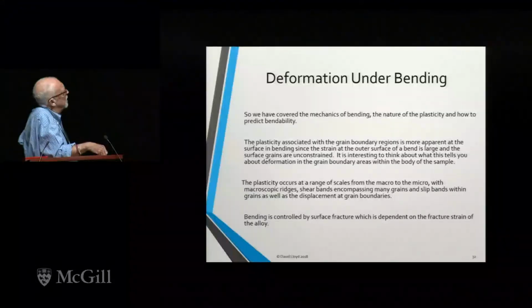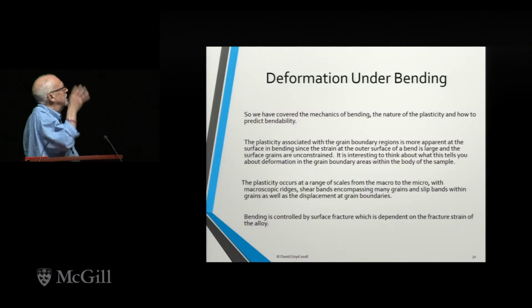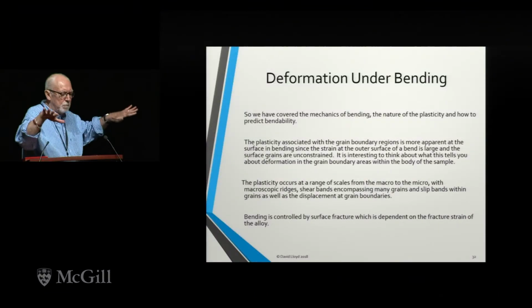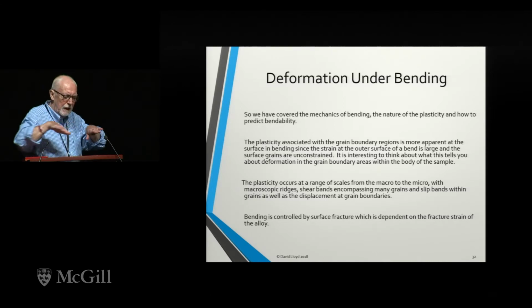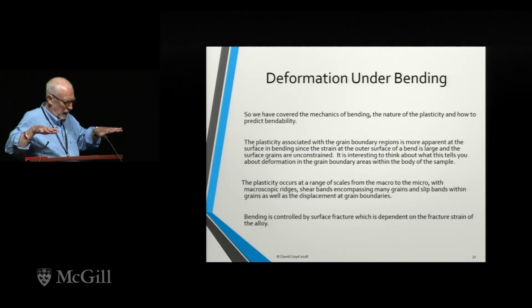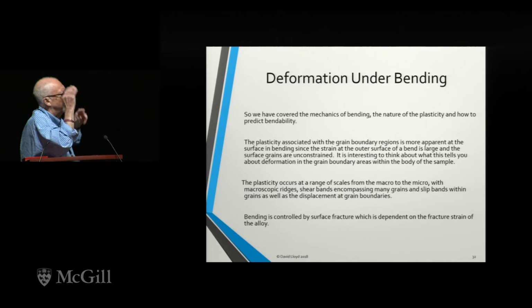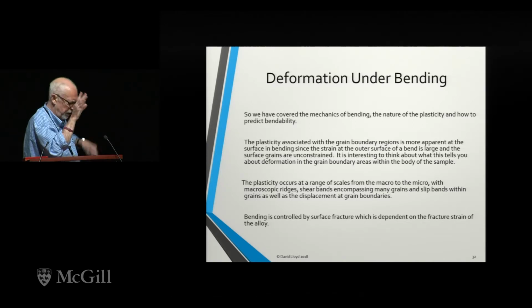Plasticity occurs at a range of scales from macro to micro, as you'd expect. There's a whole range of topography issues that I haven't even touched here, which is associated on a large scale on the bend surface. You'll see ridges and so on. But they don't appear to significantly affect anything that I've spoken about. They're interesting, and they could have a cosmetic effect in certain circumstances, if you do something stupid like having a huge grain size in the alloy.